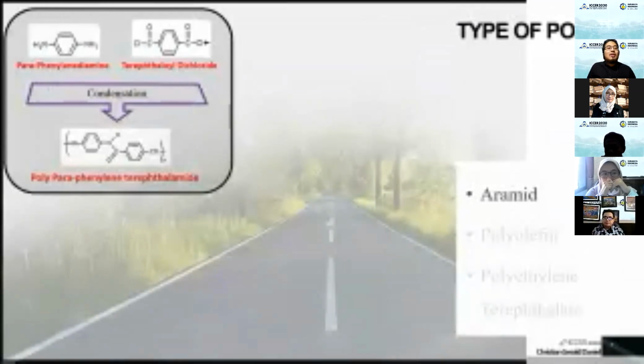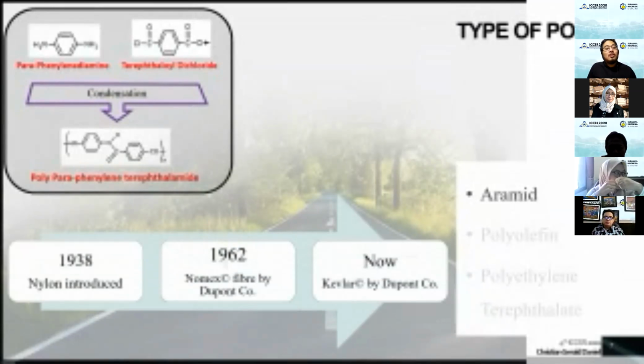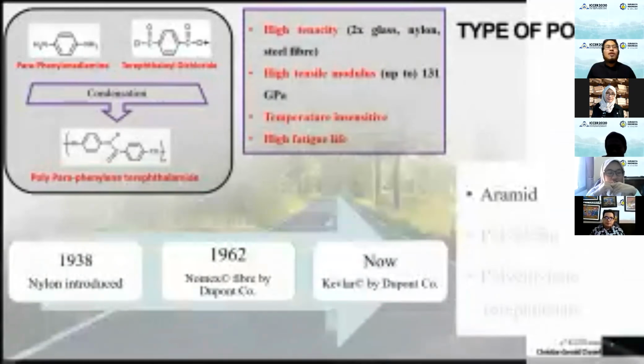For aramid, it's a result of a condensation process from two monomers. We can trace it back to the 1930s until now under the brand of Kevlar, the most notable one. And these are several of its mechanical properties. It's insensitive to temperature, which means it can really work in extreme temperature, more than 200 degrees, for instance.